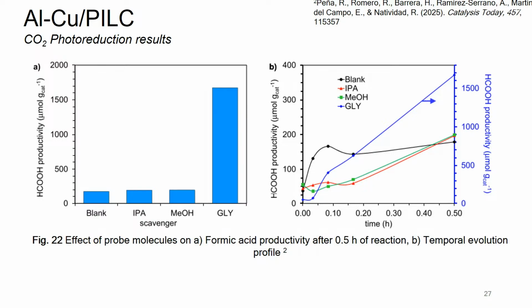In this case, with glycerol, we did a separate study on the glycerol oxidation, and we observed that the glycerol oxidation was not only producing formic acid, but it was also producing protons and hydrogen radicals. So this is telling us that the most important species that we should focus on are the hydrogen or the protons.